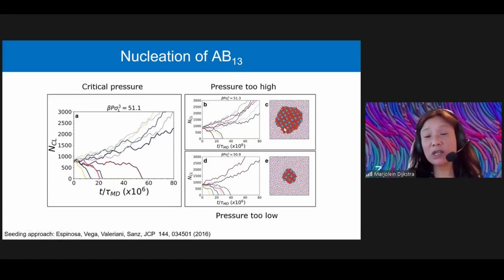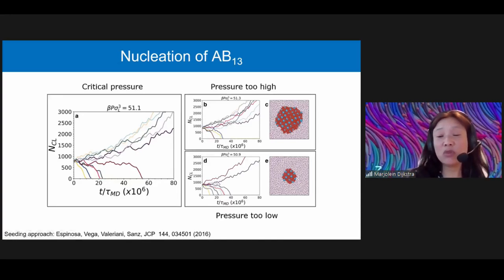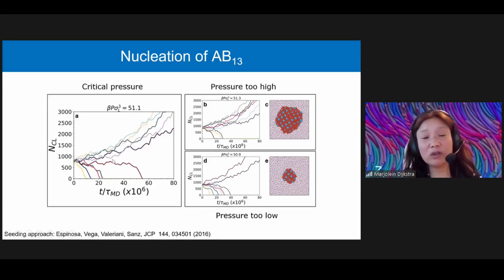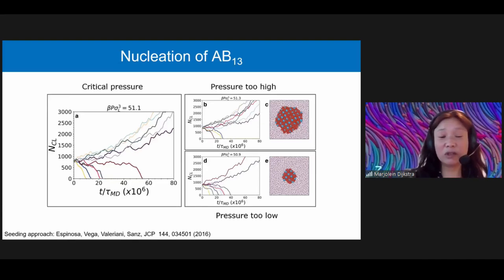So we start with a seed of this AB13 crystal. We put it in a supersaturated fluid mixture. We do Monte Carlo simulations where we fix the pressure. If the pressure is too high, most of the trajectories will correspond to a growing nucleus. If the pressure is too low, most of the trajectories will result in a melting crystal. And right at the critical pressure, half of the trajectories will grow and half of the trajectories will melt.